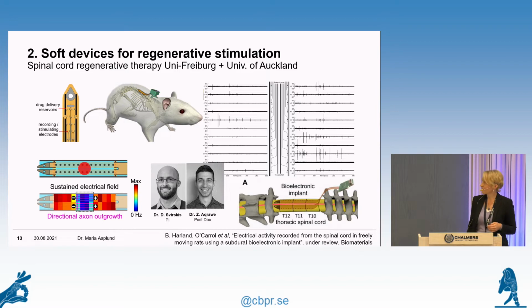So this is some preliminary data we see here on the slide. This is from our collaboration partners at the University of Auckland. They work with a rat model for spinal cord injury. And we have designed this device that is placed on top of the spinal cord, and we have just then received the first recordings after 3 months. So we can see we can record spikes from the spinal cord even after 3 months. So there's very little scarring. And as next step, we will now start to use these implants also for stimulation, so that we can then see if we can have a beneficial effect on stimulation and which kind of stimulation parameters we should use to get the most effect out.